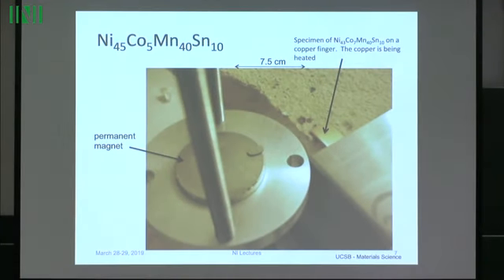Okay, so this is a little demonstration my students did. They had a little copper finger that they're heating, and they put this nickel cobalt manganese tin alloy on top of that. That's that specimen, and just heat it up. And so you go above the phase transformation temperature, it becomes strongly magnetic. So this is a material that you put on the table. It's non-magnetic. You're just below the transition temperature. You heat it up 6 degrees, it becomes a strong magnet. You let it cool down, it's non-magnetic again. Okay. So that's this demonstration.